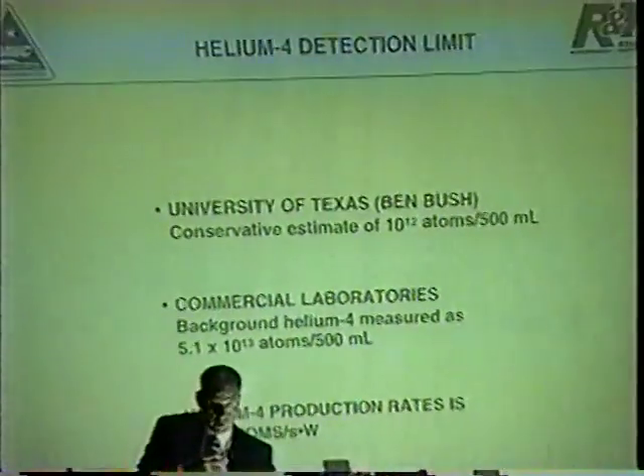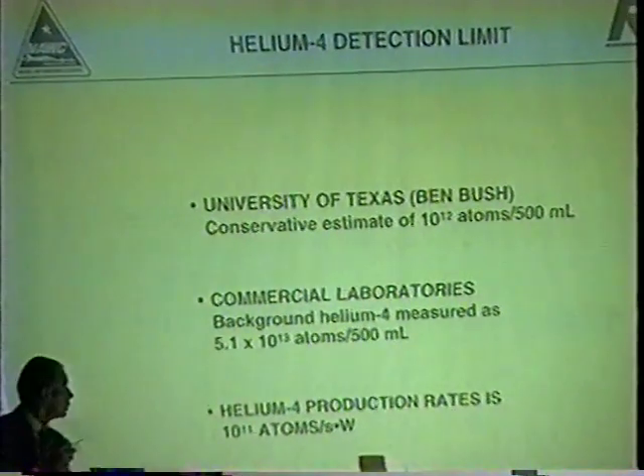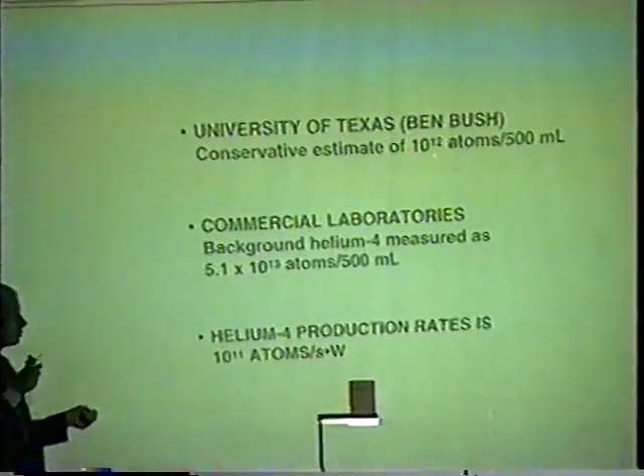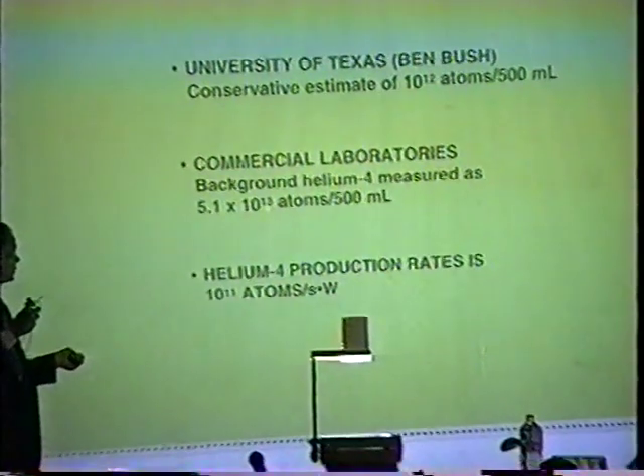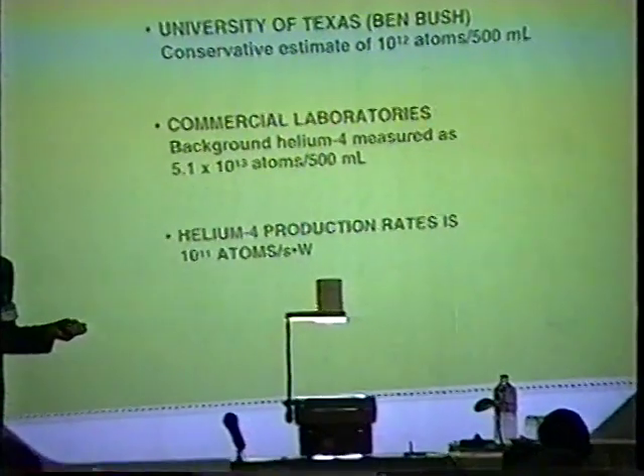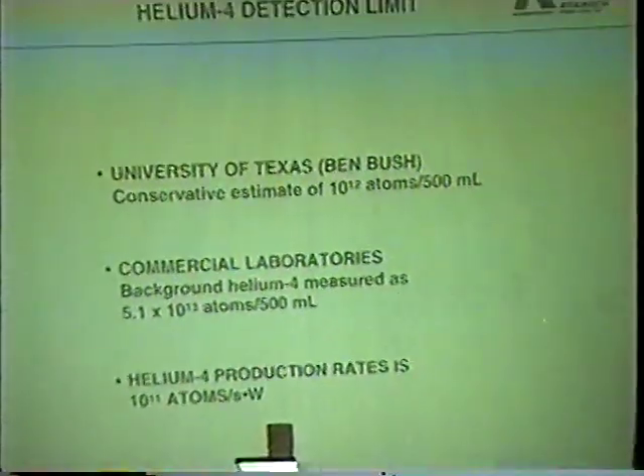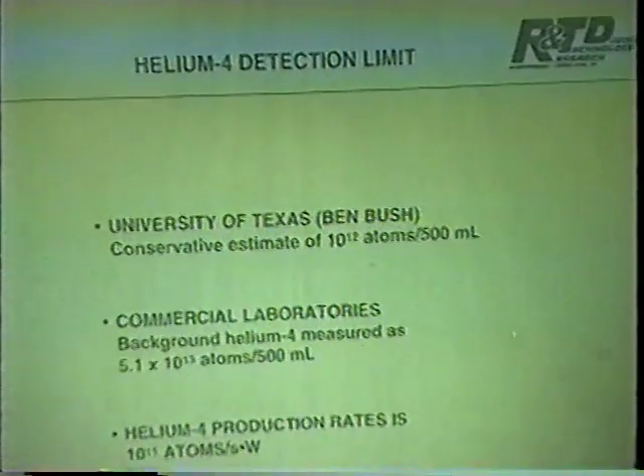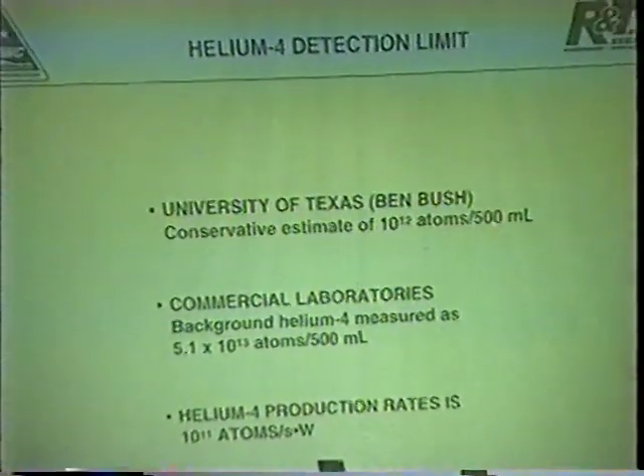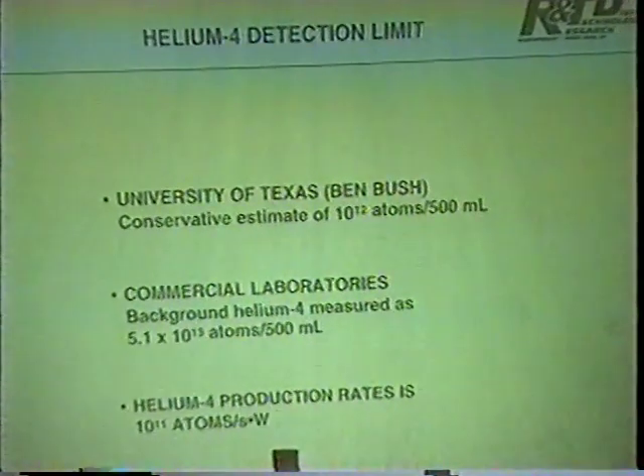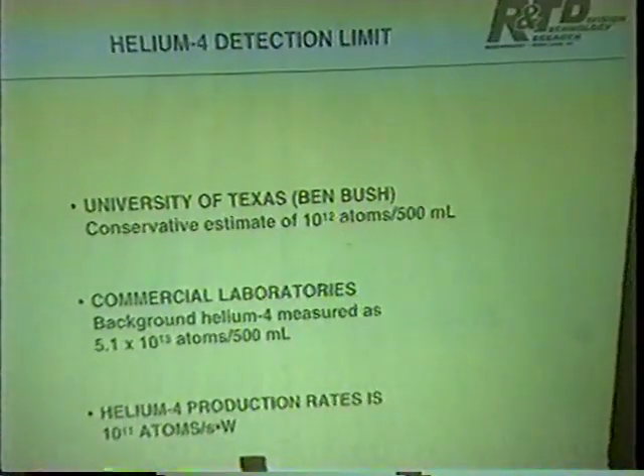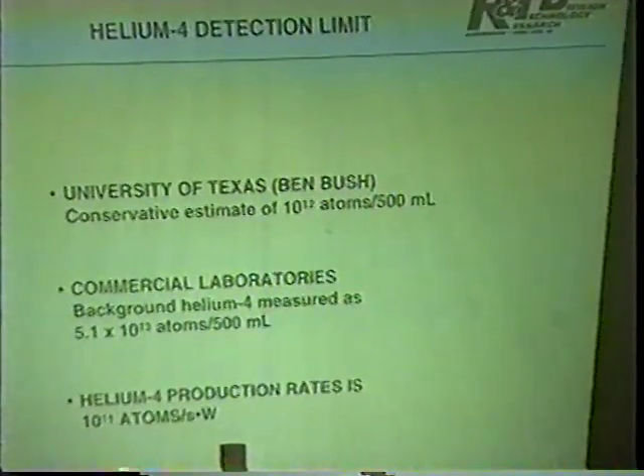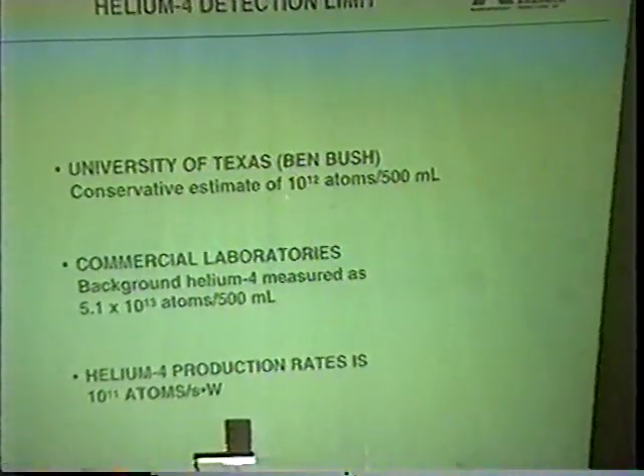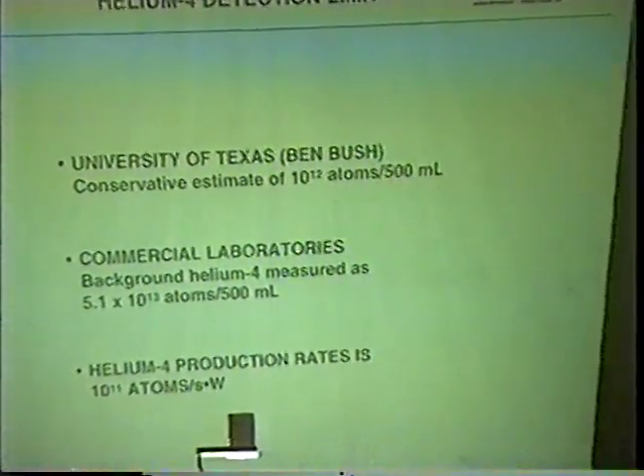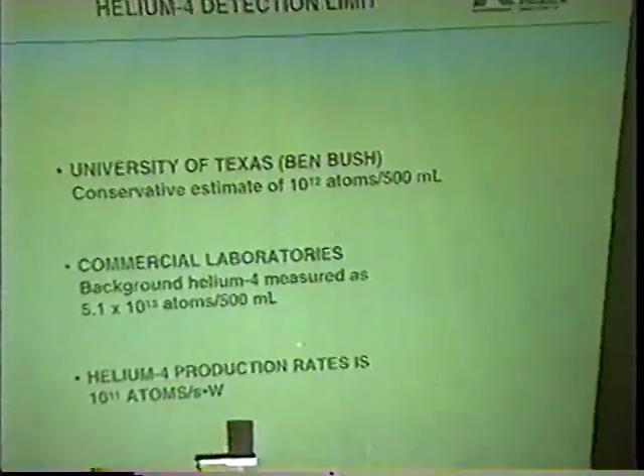He made another point about us changing our earlier detection limits. In our early results, we reported 10 to the 12. We later changed that. And we had to change it because when we did more accurate measurements of background, it was 10 to the 13. So it would not have made any sense not to change it. So our only sin, perhaps, was we were too conservative. We purposely were too conservative originally. We didn't want to claim more helium than was there, so we picked a more conservative limit. But using this background and subtracting it from our more recent results in metal flasks, we get the production rate is 10 to the 11th helium atoms per second per watt, which is about the correct magnitude.